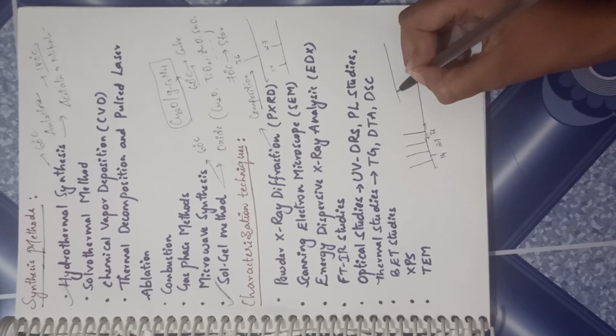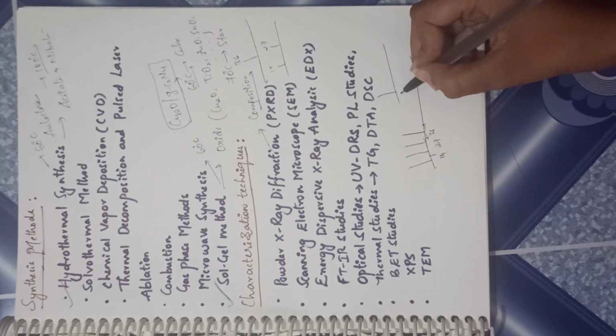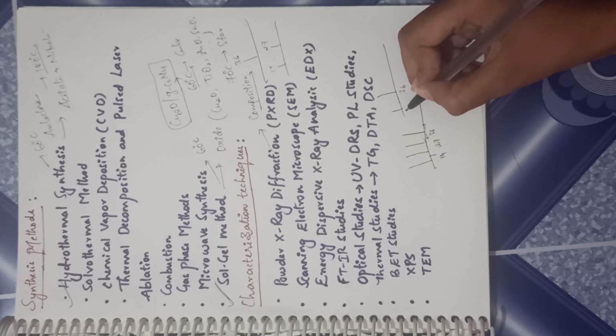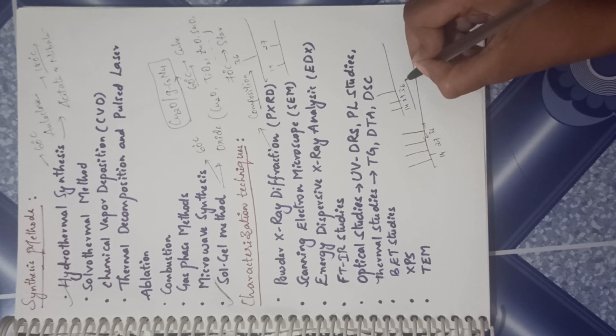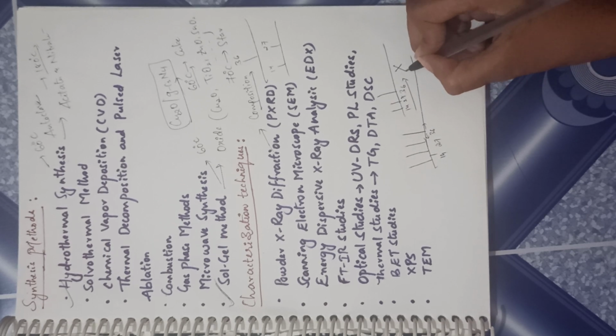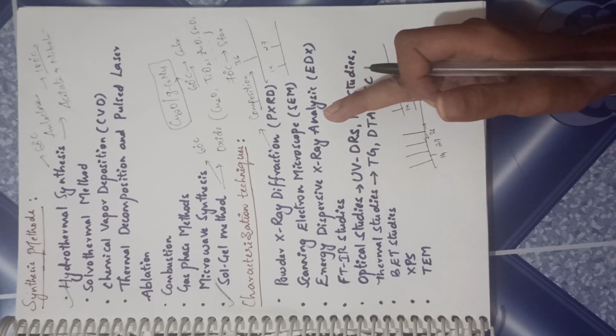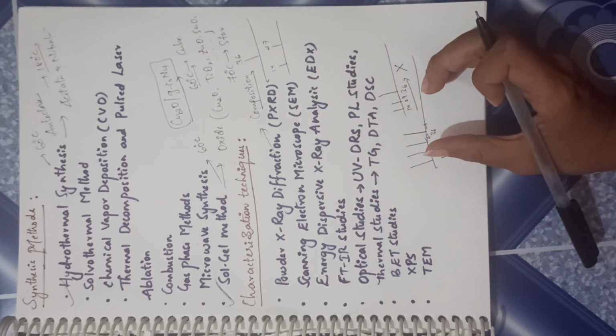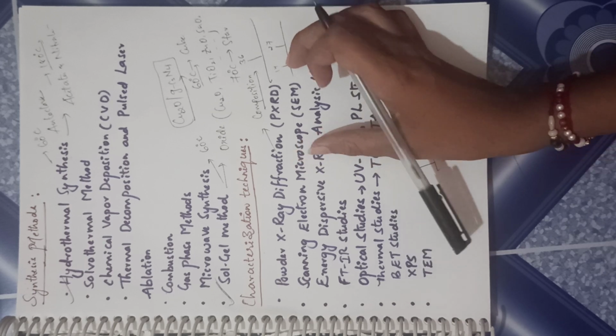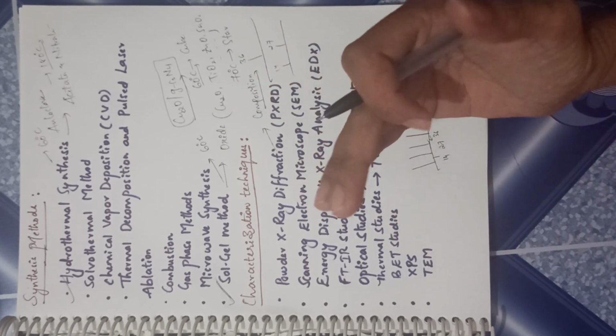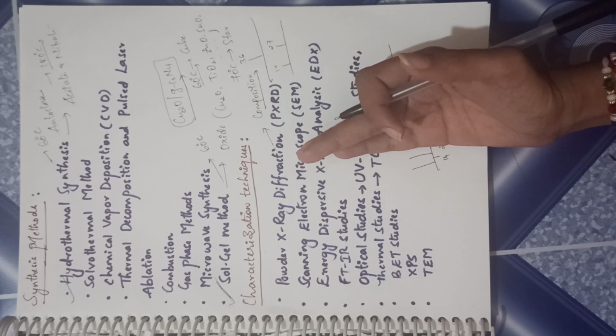Let's say if the composite is at same value, Cu2O was 36 and you got again a peak at 36 and 14 and 27, that means that the composite has not formed. There has to be either left or right shift when a composite is formed, and that is confirmed from the powder X-ray diffraction. So once you confirm that your material has formed or not, then you go for morphological studies,